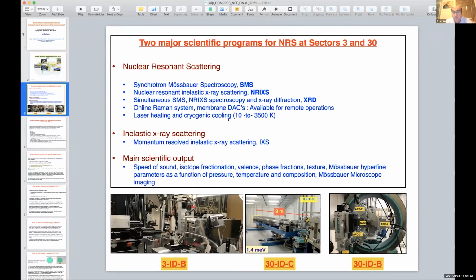We have laser heating, and we also have cryogenic cooling, so we can adjust temperatures between 10 and 3500 Kelvin. In addition, some of you have found momentum resolved inelastic scattering at 30ID useful for single crystal work. And the main scientific output we have is speed of sound, isotope fractionation for geochemists, that's of interest, valence of the Mössbauer isotopes, phase fractions in heterogeneous samples, texture, and hyperfine parameters as a function of pressure, temperature, and composition. Furthermore, we also provide microscopic imaging using the Mössbauer microscope.